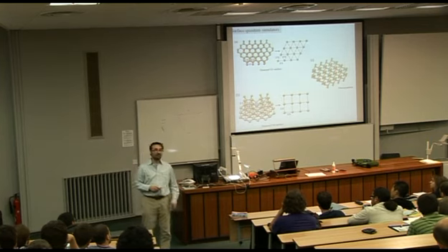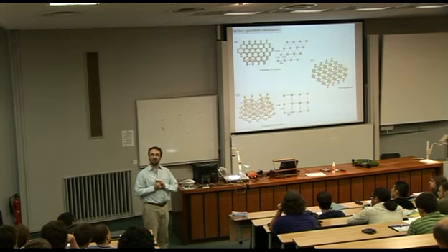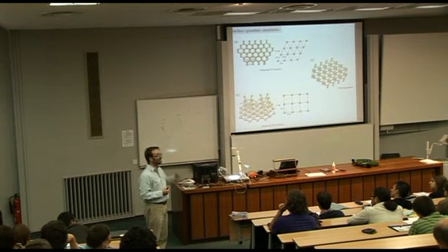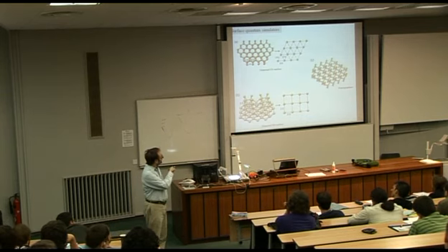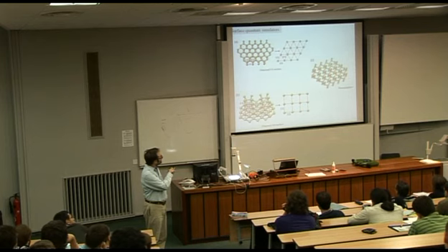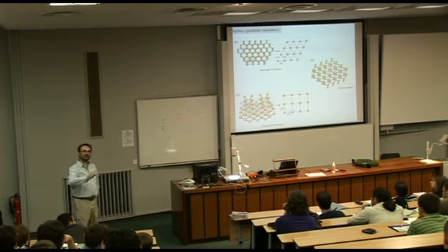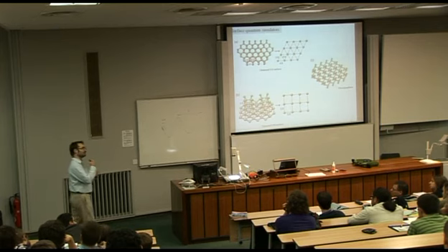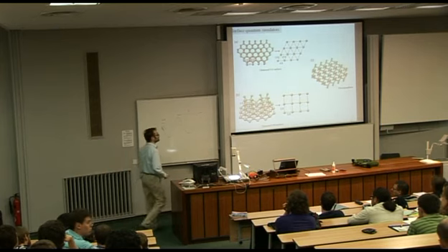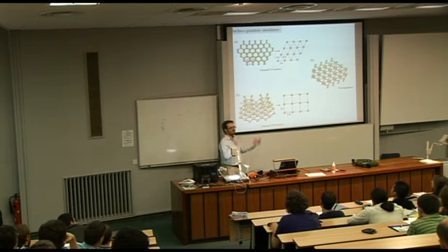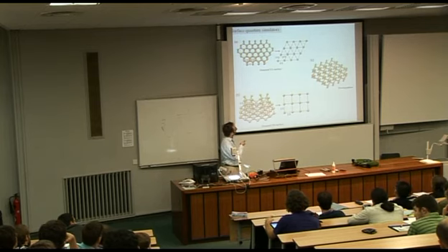And again, the nice thing is there's no optical lattice that you need here to hold these nuclear spins in place. They're just sitting there. Novoselov and Geim call this sort of Teflon. It doesn't react very much with other stuff because the fluorine really binds very tightly to the carbon. So it's really sitting there, and you really have to make it very hot to break off the fluorines again.